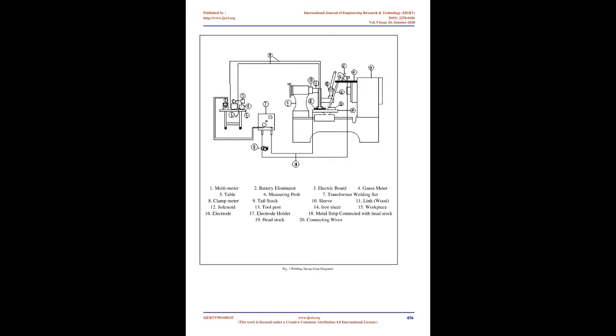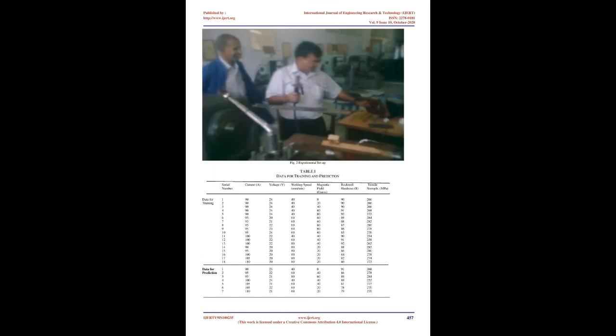in the field. In case the weld is too hard, it will lose ductility and will be susceptible to cracking. If it is too soft, then it will be susceptible to collapse or tensile failure. Hardness has a close relationship with the strength. Very much or very little heat during the welding process can change hardness and thus the strength of the weld. Thus the hardness must be right, it should not be more or less than the required value. Experience has indicated that limitations should be placed on the hardness of the base metal, heat-affected zone, weld interface, and weld metal. If the hardness is too much, these will not have sufficient ductility for the service conditions, their corrosion resistance may be impaired or some other factor may dictate this limitation.